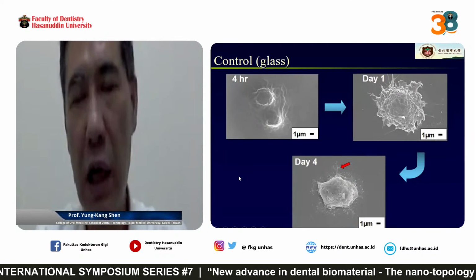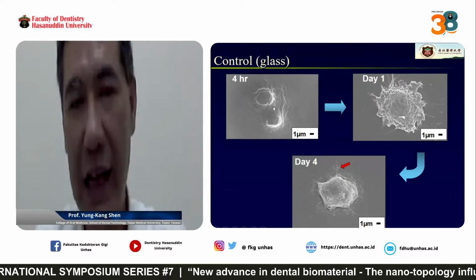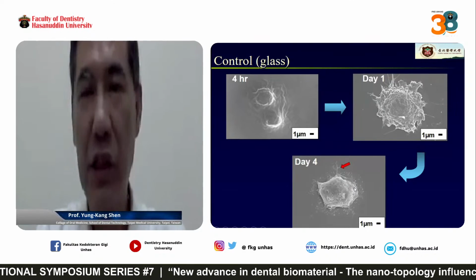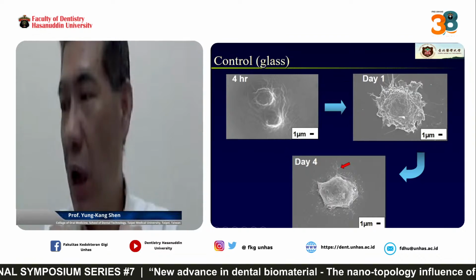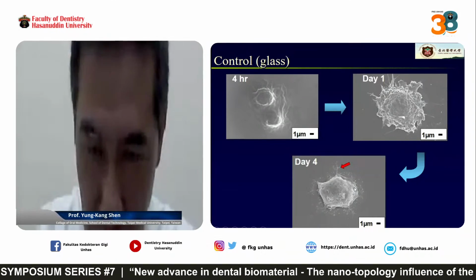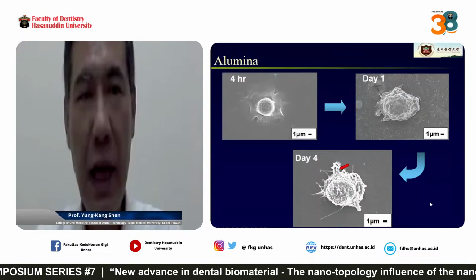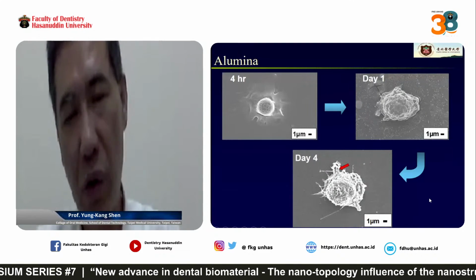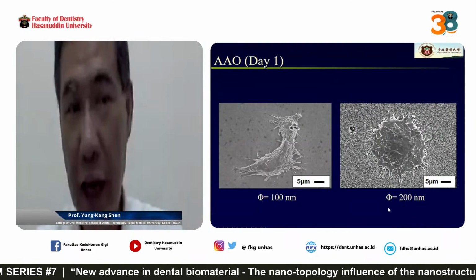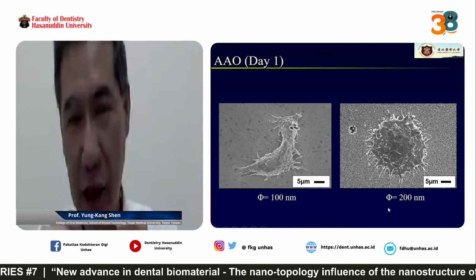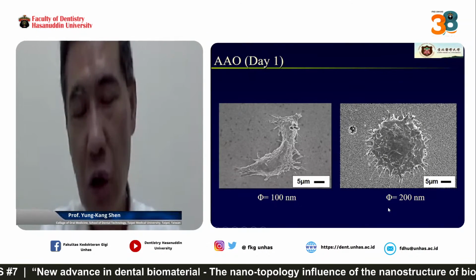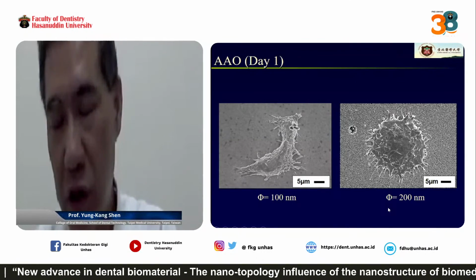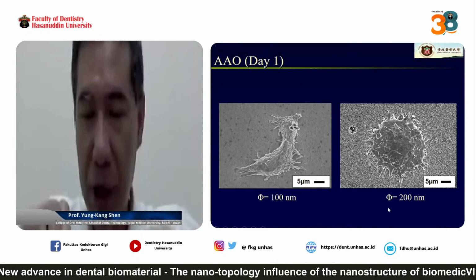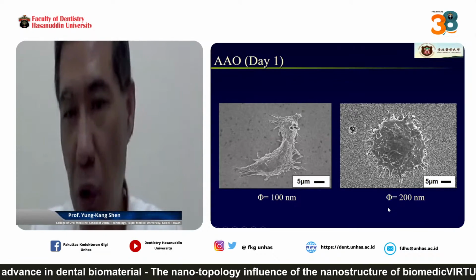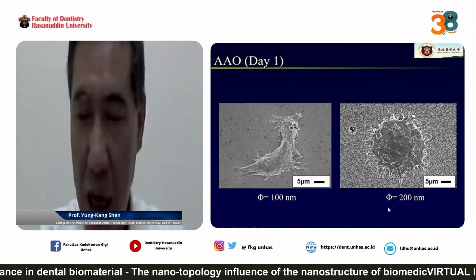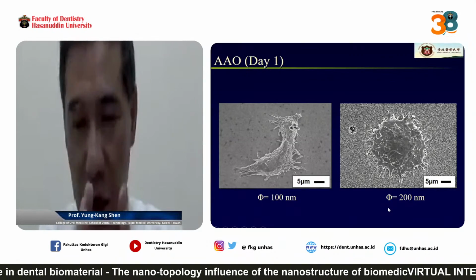Then you see the control group. This is the control group for glass. At 4 hours, day 1, day 4, you can see the cells just group together. That is not good. The cells just group together, just adhesion on the surface of the thin film. This is alumina for 4 hours, day 1 and day 4, also not good. You can see for AAO, that means the alumina has the nano hole on its surface. The left side is 100 nanometer, the right side is 200 nanometer. Maybe we can explain that there is some filopodia and growth. So this cell behavior is better than the pure alumina tablet.